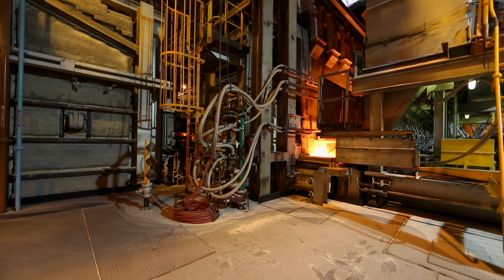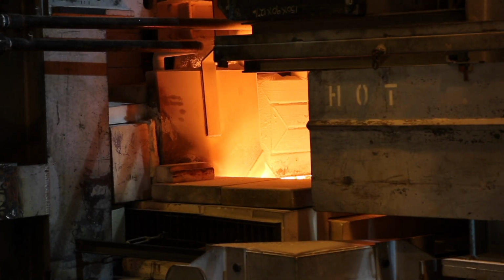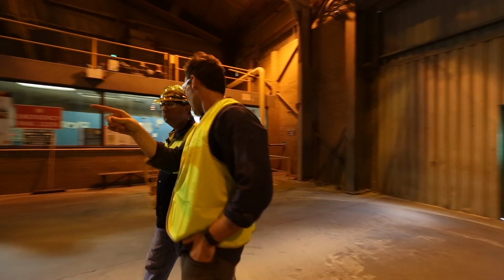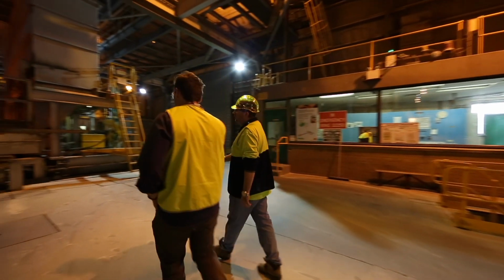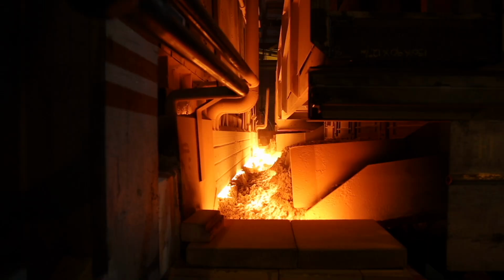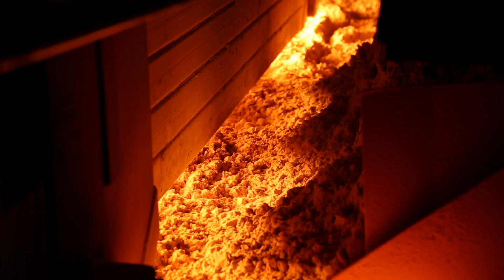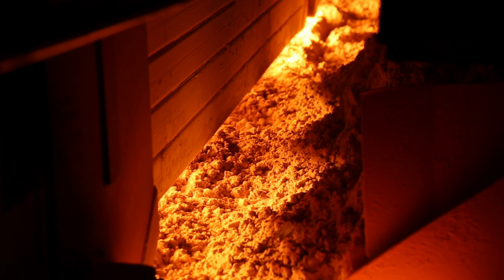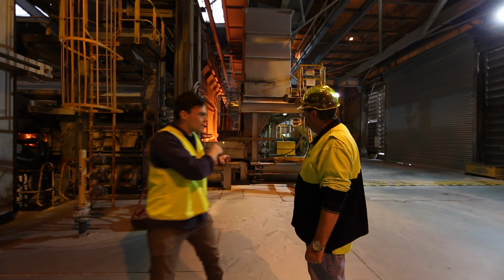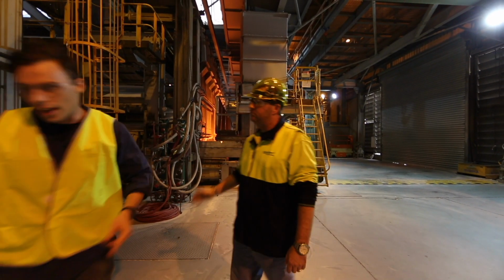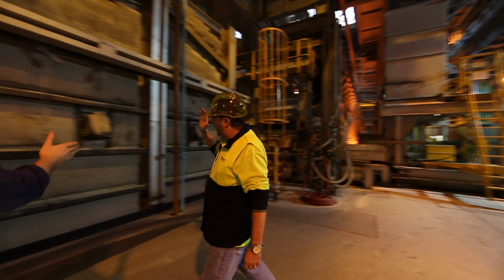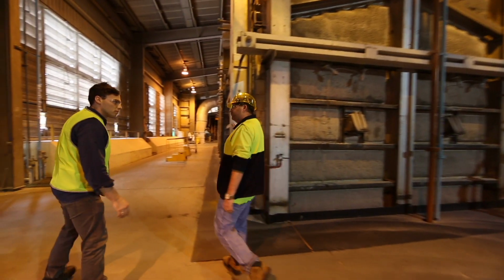Predominantly it goes into the back of the furnace. If we were to melt straight sand, we would have to melt at about 1600 degrees. And here it's about 1300, I think, isn't it? It is. Yeah. By mixing in broken glass, we gain some efficiencies with our furnace, so we can run it down to about 1300 degrees. Wow, and so in other words, the sand starts the process there? Yes. And then it's going to work its way down the kilns? So as it melts, it works its way down through the furnace.